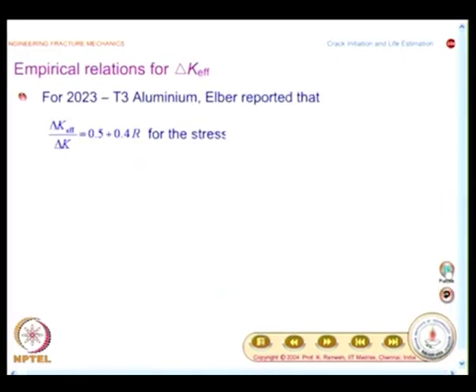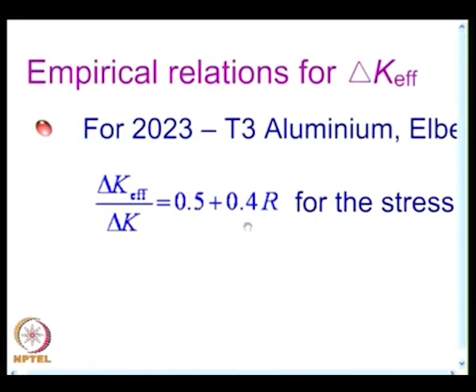So, you have empirical relations to find out what is delta K effective, and you know, for all aerospace structures aluminum is very important. So, you have a 2023 T3 aluminum. Elber reported that delta K effective over delta K can be written as 0.5 plus 0.4 R, where R is the stress ratio, and he had obtained the relation for the range R between 0 and 0.7, and there are also other researchers who have extended this range of R. But the point to note here is, you need to have some way of finding out what is the value of K effective. If necessary, I can also enlarge it. So, this is the equation that you have.